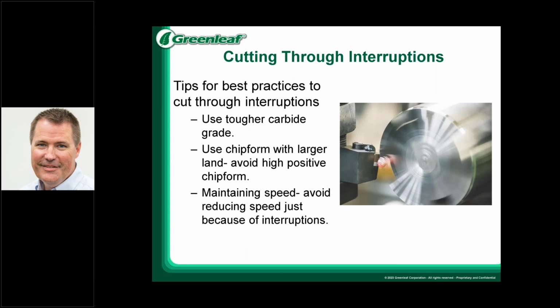Wanted to talk a little bit also about cutting through interruptions. We mentioned it as being present for the wear that you may see on carbide inserts. Some of the tips here you can see: using tougher carbide grades, finding a grade that has the larger grains of carbide in there will help it hold up better. The cobalt that's mixed in actually provides a little bit of a shock absorption for the insert itself.